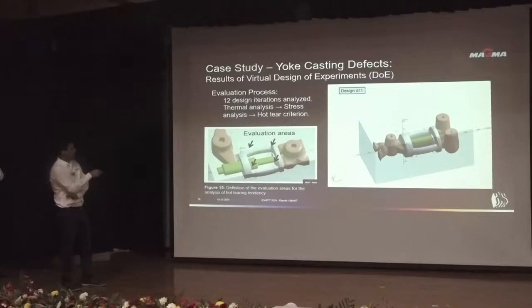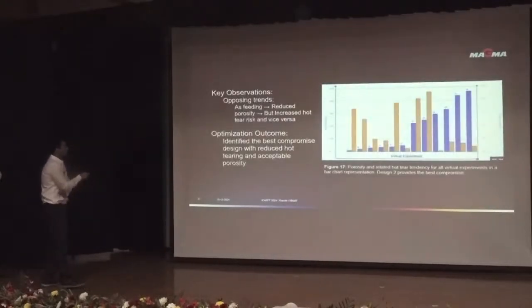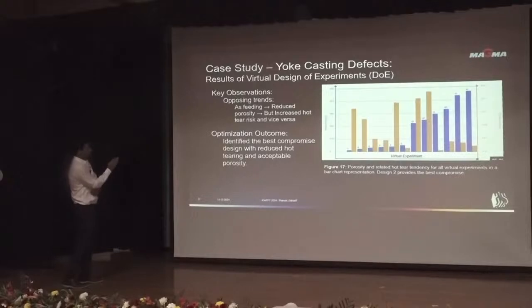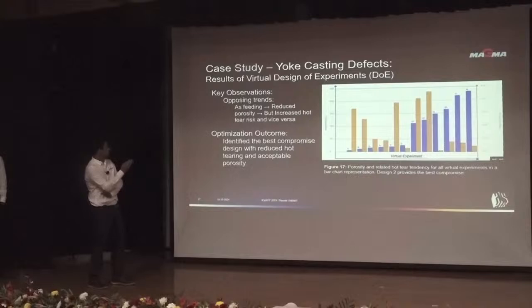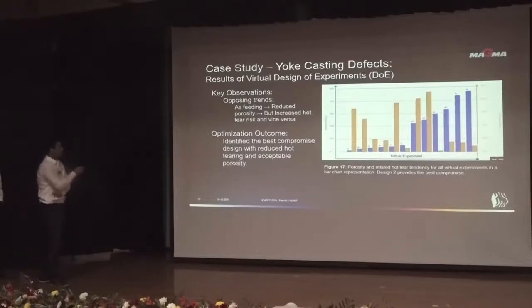So what are the results we got? These were the comparisons between all the results, where on the left we kept reduced porosity, and on the right we kept reduced hot tear. It shows there is an opposing trend: if we increase feeding, that reduces porosity but increases the hot tear, and vice versa. So what is the optimized outcome? In the middle you can see a compromise state where we have less porosity and less hot tear effect.